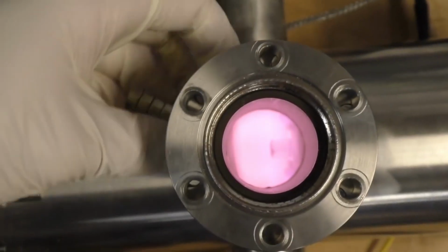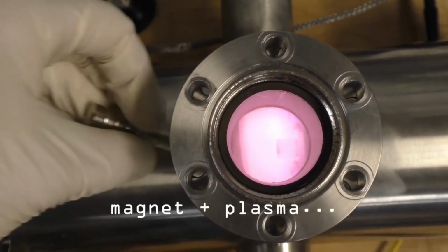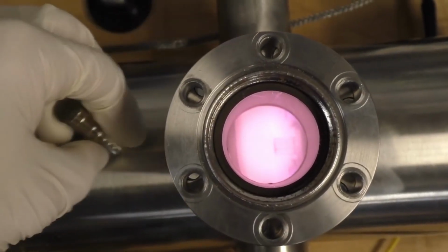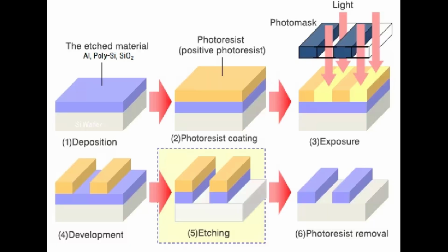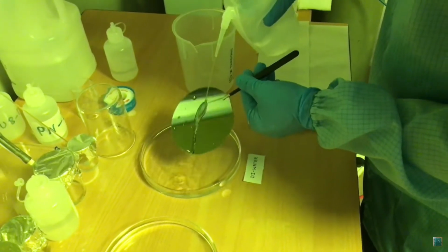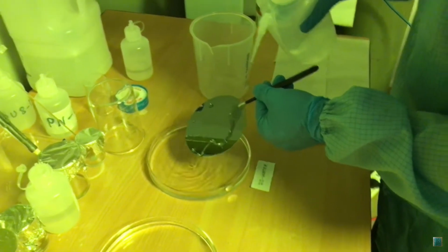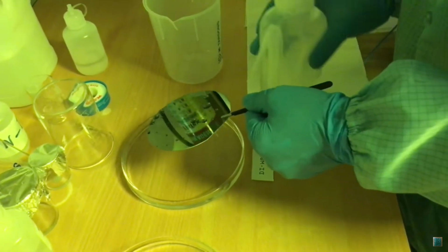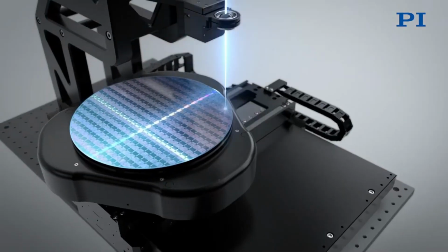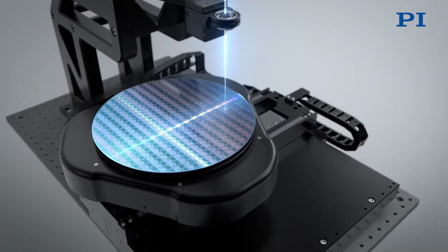We then place this wafer into a developer, just like how you would with a photograph to make the picture come out clearer. And then we place this entire wafer into a reactive ion etch, where an SF6 plasma will eat away at the parts of the metal that are not protected by resist, leaving exposed silicon trenches where resist did not cover. Wash the remaining resist off the wafer with an acetone and an isopropyl bath. And then you can dice the wafer to get your individual chips.